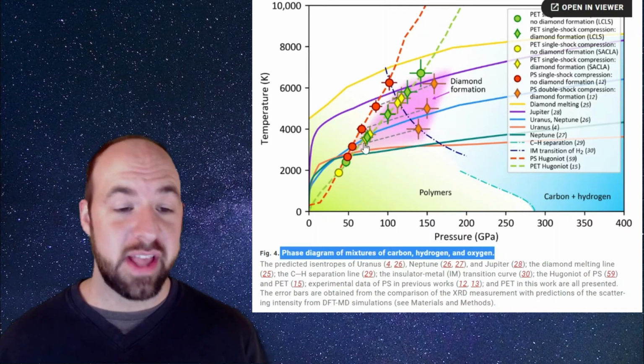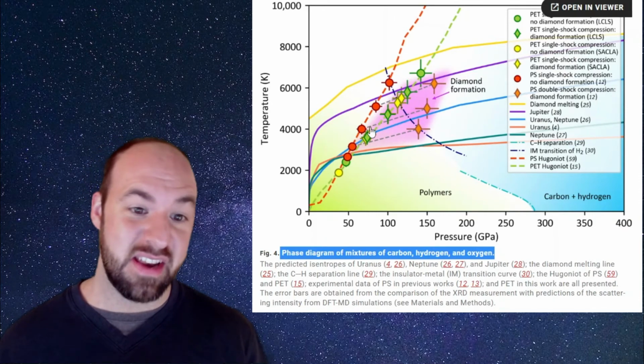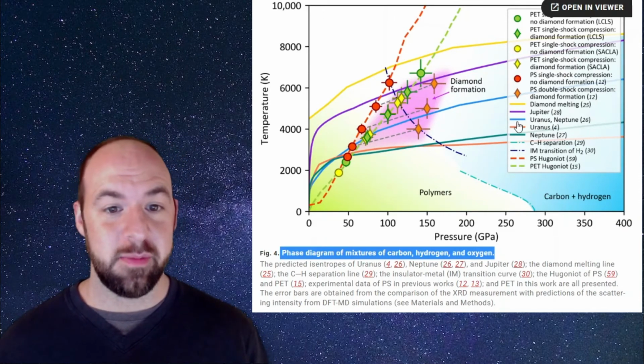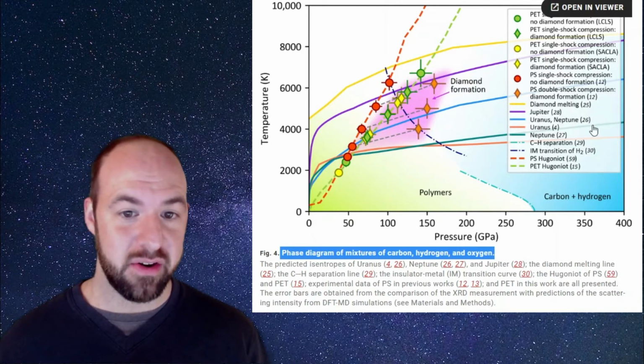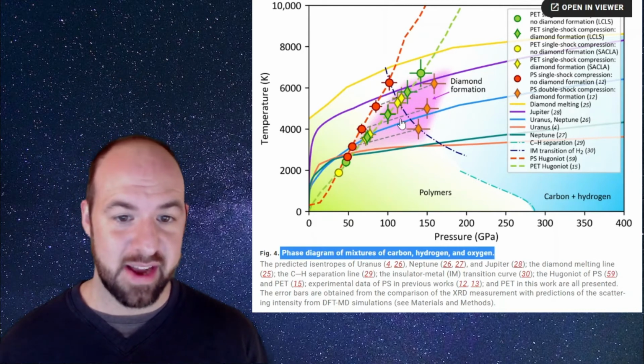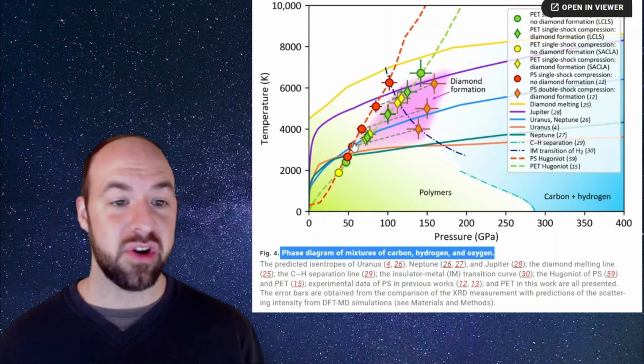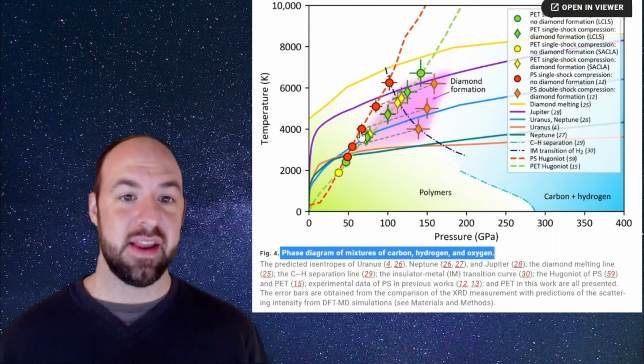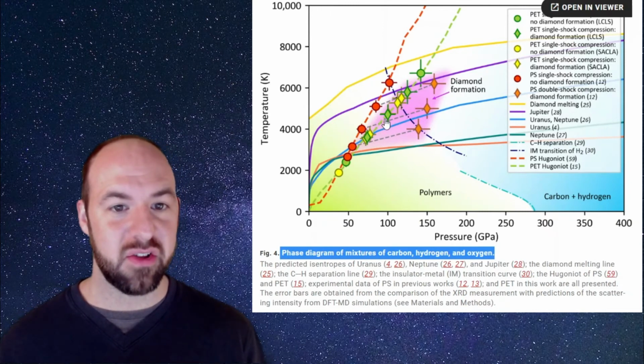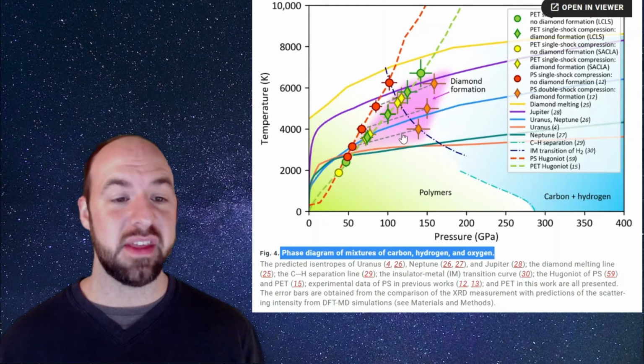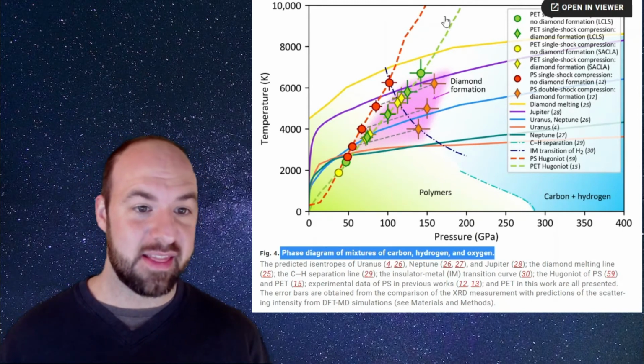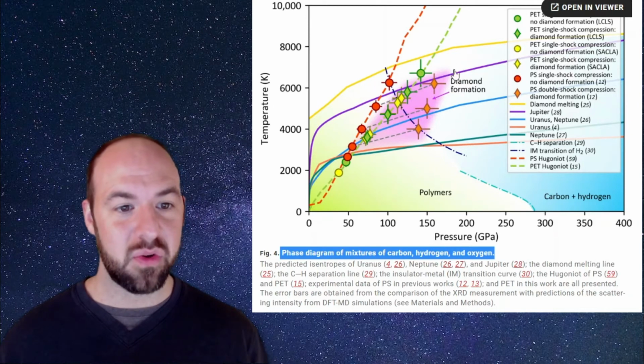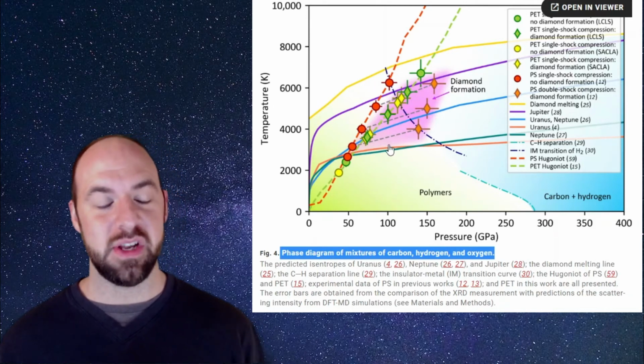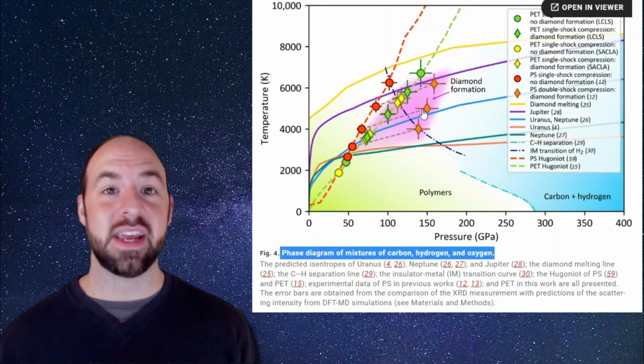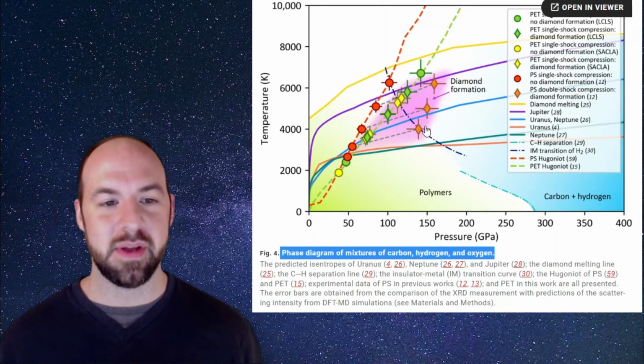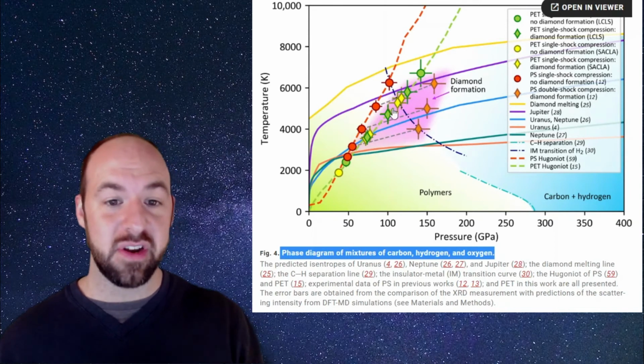And then we have overlaid on the same figure lines that represent the pressure-temperature regimes of different planets. And so you actually see the blue line here, according to some sources, is the pressure and temperature region for Uranus and Neptune. And overlaid with that are these green and yellow triangles and whatnot, which show the actual conditions of the experiment. So the fact that these two lines, the dotted green line and the blue line, intersect in the diamond formation region shows that they're similar enough that you're getting similar conditions during your laser shock experiment that actually emulates the conditions of Uranus and Neptune.